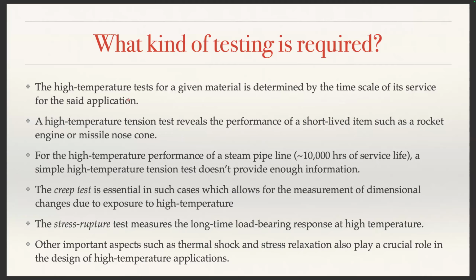Gas turbine engines, creep? So based on operating temperature only we have to decide. No, it is supposed to be, operating temperature is going to be very close to your melting temperature. It is going to be more than 0.5 times the homologous temperature. Not the rocket engine, but gas turbine engines do go for thermal creep. Rocket engine need not be, because the amount of time that the rocket engine is operating at that high temperature is very short-lived. So that is why what kind of test is required in order to decide whether this component is suited for creep application depends on the time scales of its service.